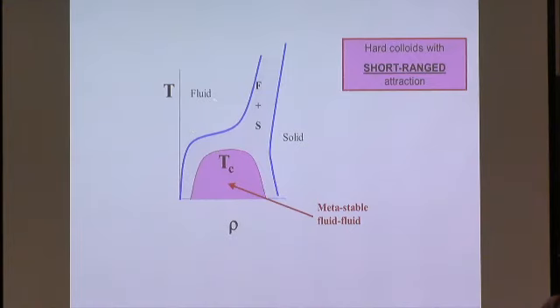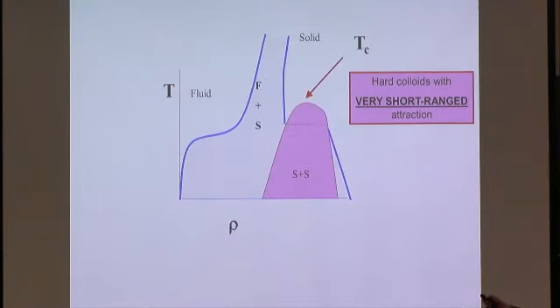Now even that's not what I'm going to talk about. What I'm going to talk about is what happens if you make the range of attraction very short. Not unphysically short, it's experimentally possible to do it. If you do that, then you get something that mirrors the liquid-vapor transition, but it's on the solid side. You get a transition between two solid phases that have the same symmetry, the same structure, for instance face-centered cubic. And the transition between them is only a transition between phases with a different density.